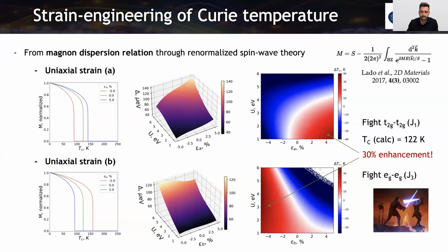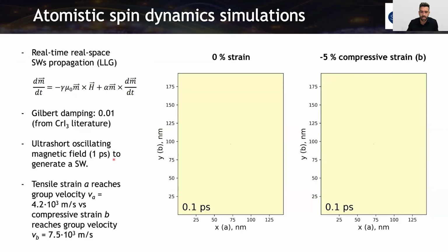So the best strategy for increasing the Curie temperature in this material is just expanding along the A-axis, whereas in B, we have the opposite behavior. So this is clear. And this white part here is because we could stabilize the antiferromagnetic ground state in chromium sulfur-bromide with extreme Hubbard-U calculation. Then regarding the spin dynamic simulation, we apply the Landau-Lifshitz-Gilbert equation.